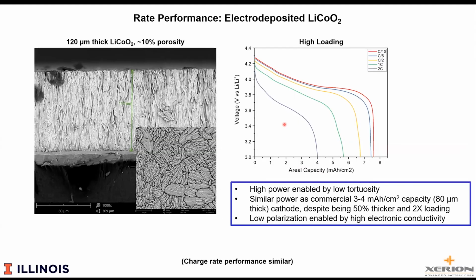A little bit about rate performance. This is a very thick electrode, so if we want to talk about high rate, this is now a system here where these are different discharge rates, and one can see that up to about 1 C, so this is a 1 hour discharge, the capacity is pretty good. You might say that's nowhere near commercial. I'll show you commercial benchmarks. But this is twice the capacity and 50% thicker than you would use in any commercial electrode. So this is really a high energy design, but a high energy design that has much better power performance than you would normally get.